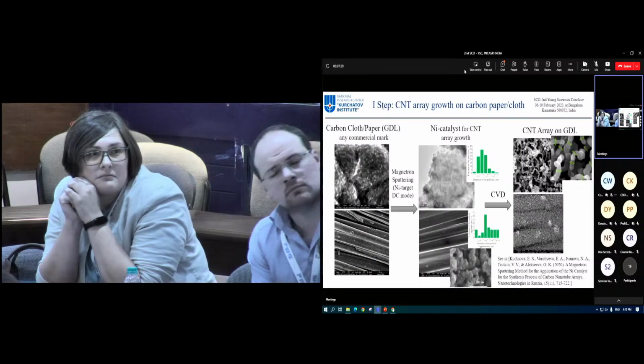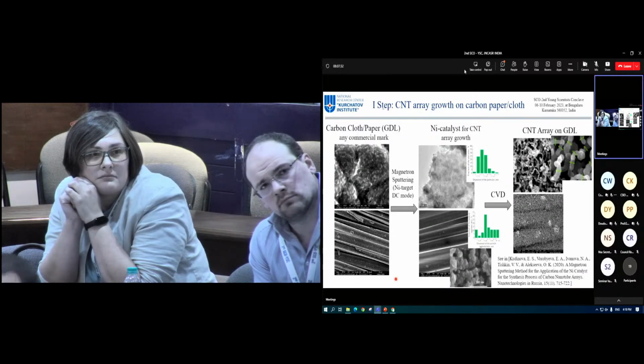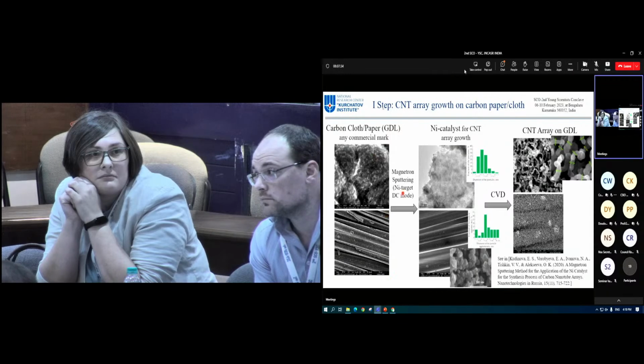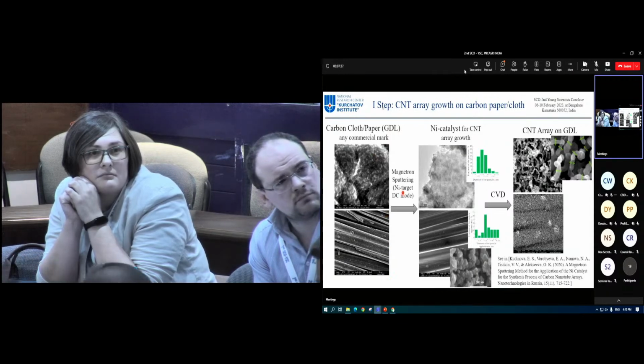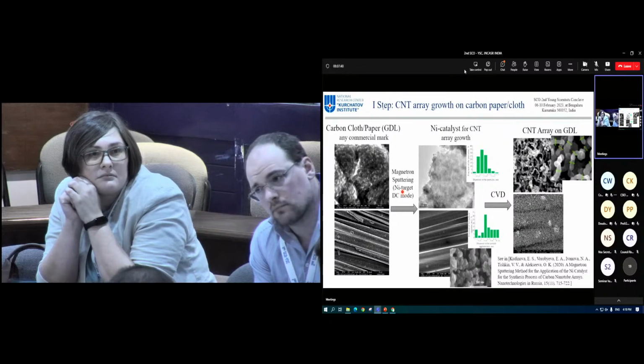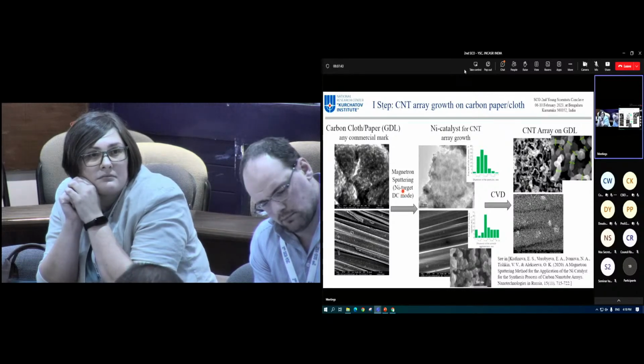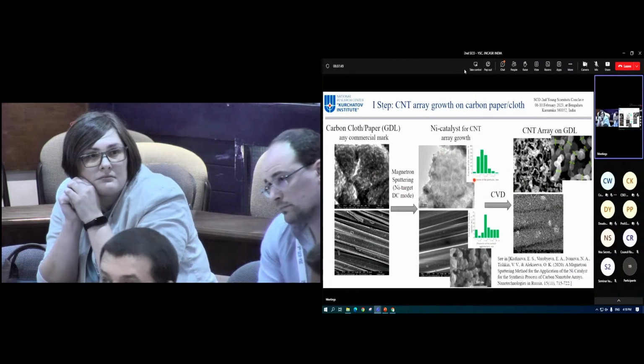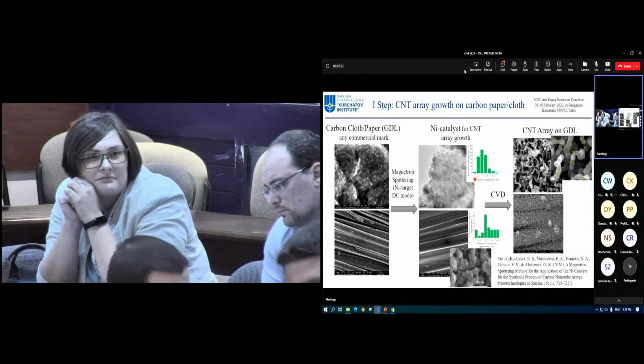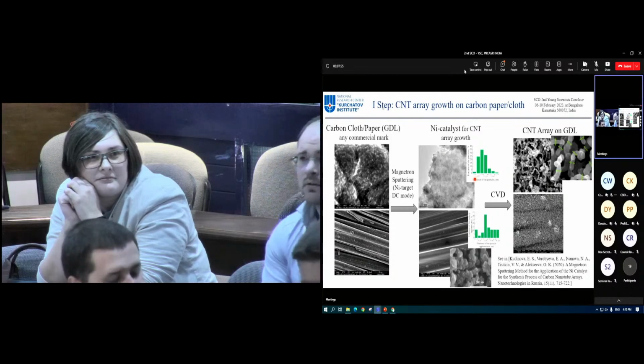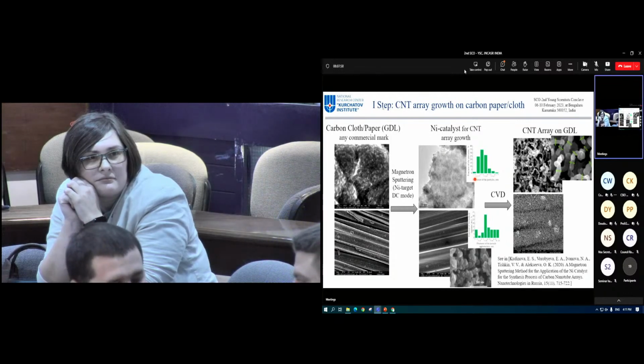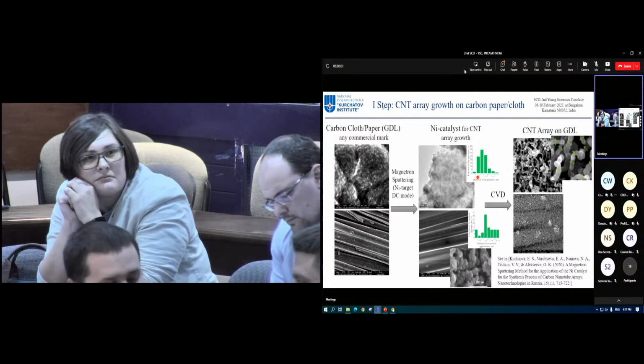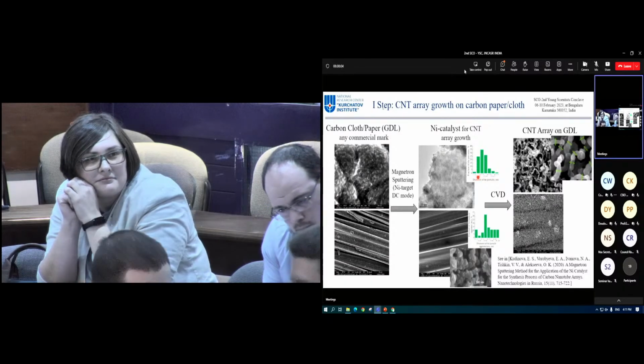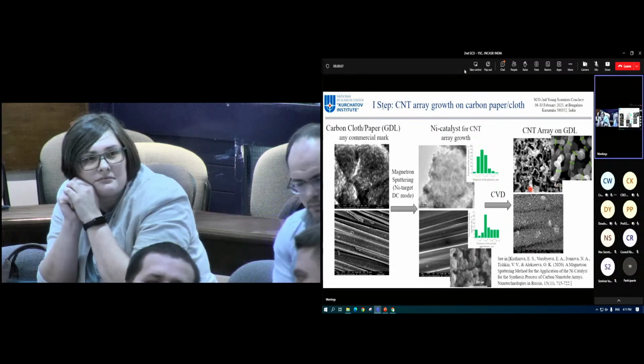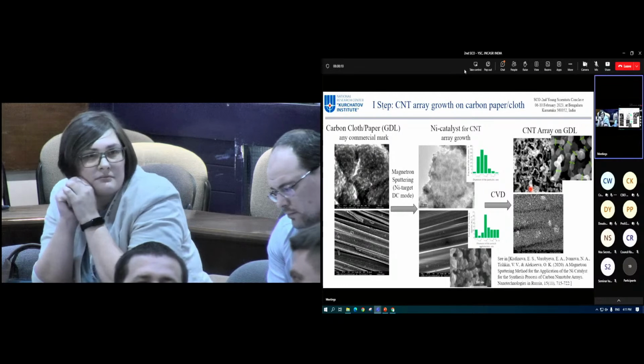The first step is CNT array growth on carbon paper or cloth. Magnetron sputtering in direct current mode is used to create a compact nanostructured nickel film with an average particle size of 3 nanometers. The obtained compact, highly uniform distribution film with a low specific surface and a narrow nickel agglomerate size distribution has been successfully used as a catalyst for the growth of CNT arrays in the process of pyrolytic gas phase deposition directly onto the gas diffusion layers. The diameters of the obtained nanotubes are 40-60 nanometers.